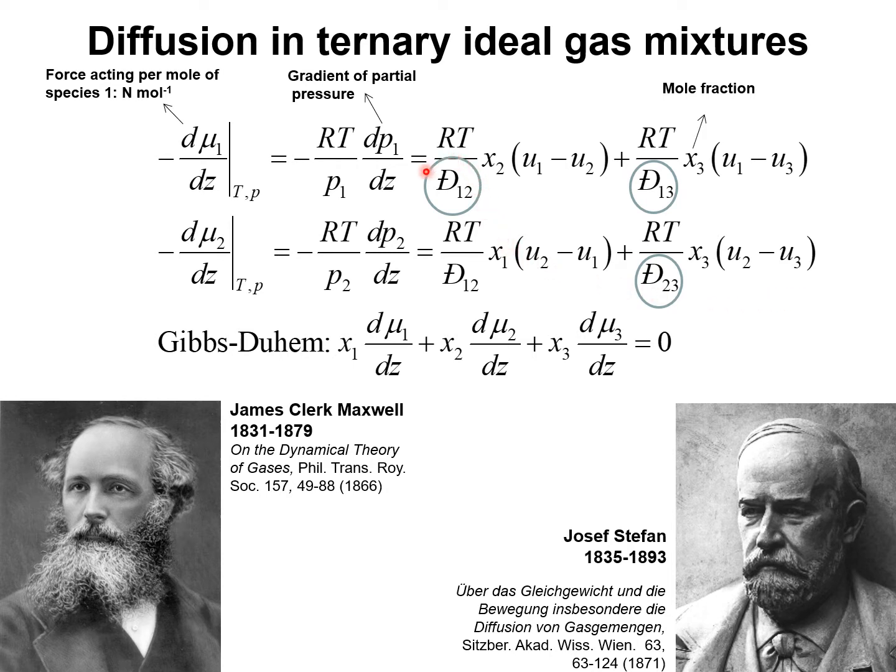We define the Maxwell-Stefan diffusivities in this manner, and the Maxwell-Stefan diffusivities are differentiated from the Fick diffusivities by using the symbol D with a line through it. On the basis of this formulation, it is evident that the physical significance of the Maxwell-Stefan diffusivities is that it represents an inverse drag coefficient.